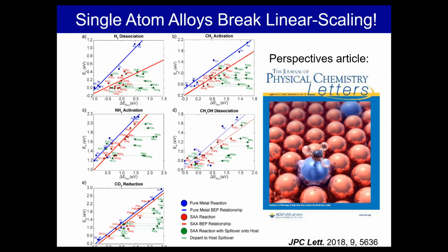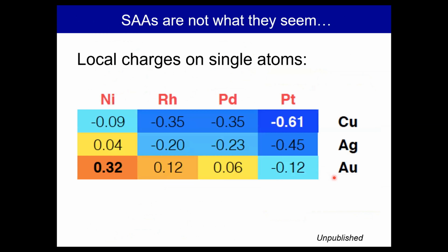Now, as the last 2 minutes, why are these things so different? Why are we getting all these different properties from this atomic geometry? Now, it's not quite what you would intuitively think, because one of the things we found from the DFT calculation is if you use Bader charges and just look at the charge on, for example, a single platinum atom in copper, it predicts it has more than half an electron charge negative on the platinum and the copper versus nickel and gold, which has a deficiency of 0.3 of an electron. And this is basically because you're putting dissimilar elements together which have different ionization energies, electron affinities, and so on, and you do get charge transfer between them.